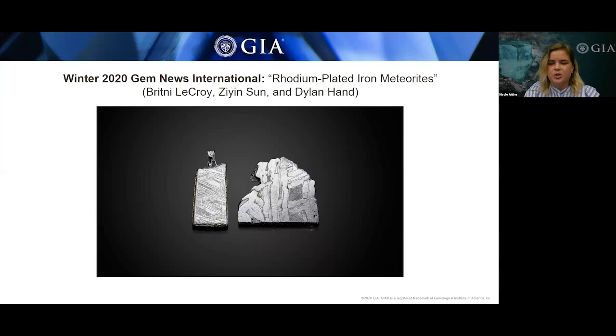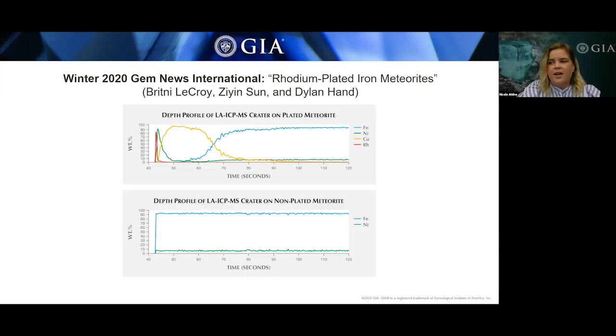So pictured here, we see two rhodium plated iron meteorites, a 28.53 carat mounted pendant and a 36.69 carat loose slab. They were acquired by one of the authors during the Tucson Gem and Mineral Show in 2020. With the pieces having an abnormally high metallic luster and bright white color compared to a typical polished and etched meteorite, they were suspected to be imitations of iron meteorite. Chemical analysis of the elements using LA-ICP-MS revealed that the two pieces were authentic etched iron meteorites that were plated with metals including nickel, copper, and rhodium.